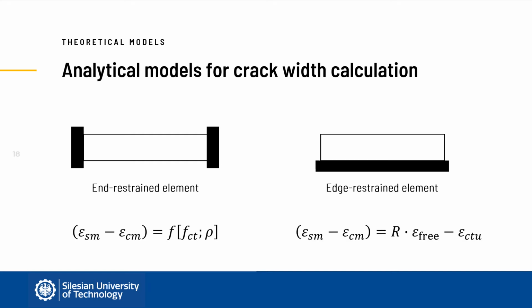The other scenario is that of an element restrained at its base. In this case, cracking changes forces locally, and the crack-inducing strain depends on the restrained part of the strain and extensibility of concrete, which means the ability of concrete to expand between the cracks.